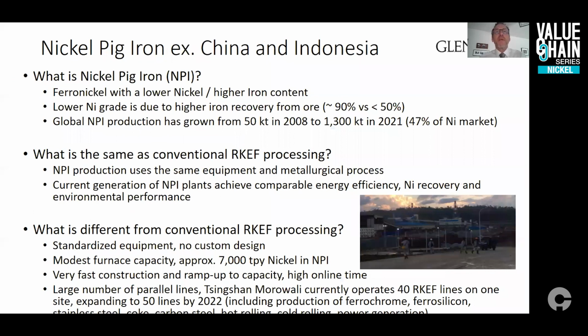Nickel pig iron, or NPI as it's known, is not really a new product. It's ferronickel with a lower nickel and higher iron content. The lower nickel grade stems from higher iron recovery in the smelting furnace, typically around 90% in an NPI operation, compared with less than 50% in a conventional laterite smelter producing ferronickel. Global production of NPI has grown to supply nearly 50% of the nickel market in less than 15 years.